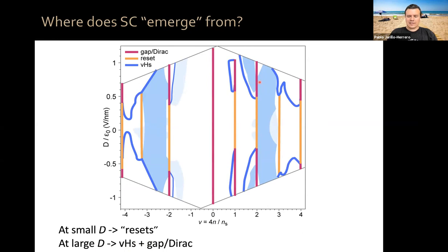Okay? So then that tells us the following. By analyzing this displacement field dependence, what we have realized is that superconductivity emerges upon doping the filling factor 2 phase, which has a broken flavor symmetry ground state with two Fermi surfaces. What do I mean by that?